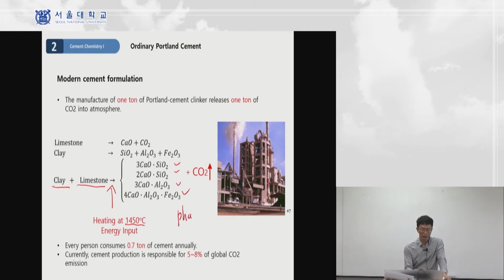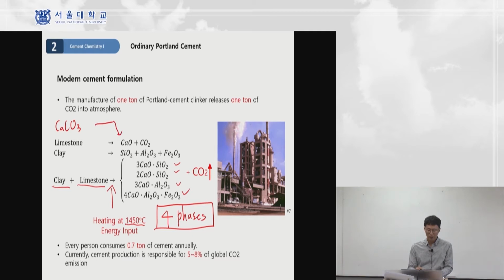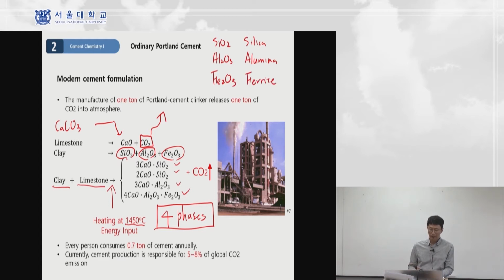These are called phases. Mainly we can get 4 main phases. Limestone will be decomposed, because limestone's chemical formula is CaCO3, and it will decompose into CaO and CO2. The CO2 will be released, right? And the clay, mostly the oxide composition is silica, alumina, and ferrite. So this one is silica, alumina, ferrite. Si means silicon, right? SiO2 indicates silica, Al means aluminum, and Al2O3 means alumina, and Fe is iron, and Fe2O3 is ferrite.